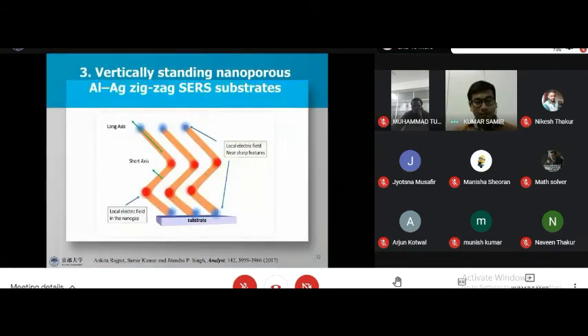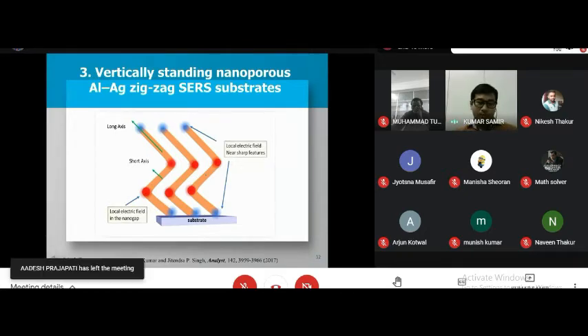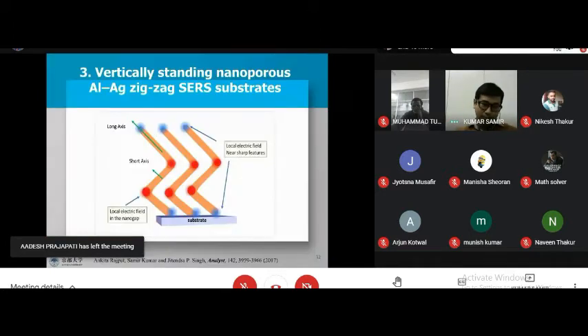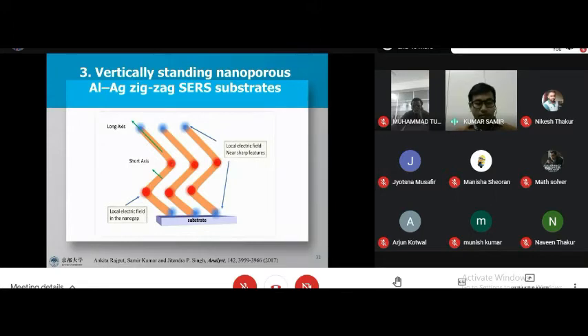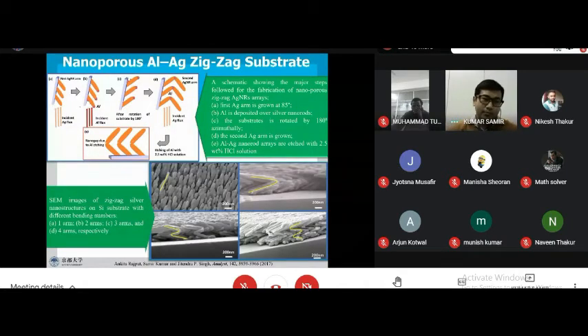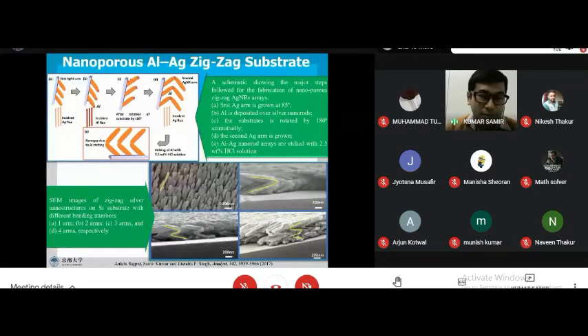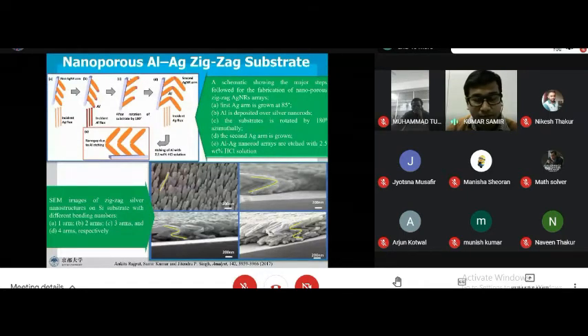And the third part is the vertically standing silver zigzag substrate. For this we fabricated two types of nanostructure. One is a pure silver zigzag nanostructure, and for the second nanostructure, we grew a small amount of aluminium at the elbow between these two silver arms. So the first structure is purely silver, and for the second, we first grow one silver arm, then grow around 50 nanometer aluminium, then rotate it by 180 degrees, and again deposit silver. Like this, we grow one arm, two arm, three arm, and four arm zigzag nanostructures.